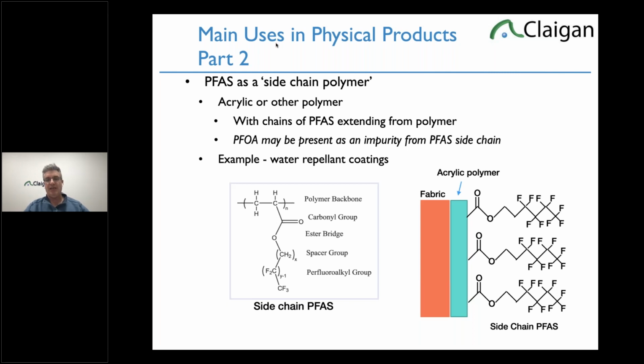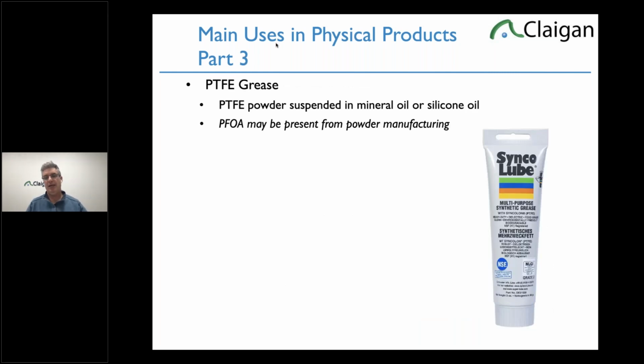It's very advantageous. The downside is when it's made, it could have some chemicals break off and become trace levels of PFOA. That's probably manageable actually, and it's extremely trace. That's not going to affect your kidneys. But it is measured in Prop 65, and there were a number of prosecution notices around that. Very common in a lot of products is PTFE grease. It's basically PTFE powder, like the original one.